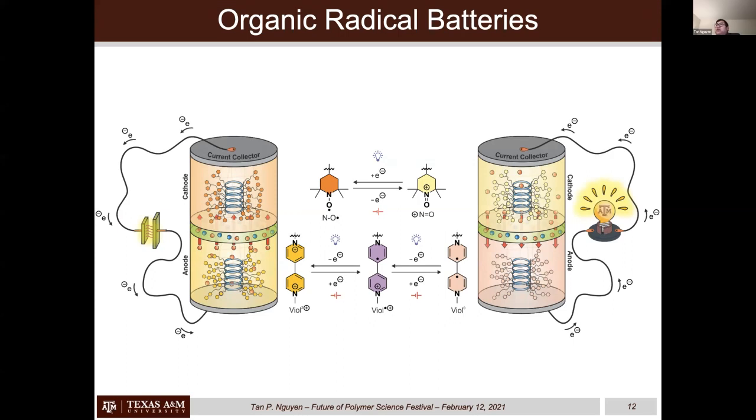So you're correct that our capacity relies heavily on what processes we can go down to. But for our system, the biggest problem is the dissolution of the material into the electrolyte. So we thought about decreasing the voltage window, but with the dissolution, it doesn't really matter what window we approach. It always happens. The capacity always fades too fast. I think that's the biggest problem we have right now.